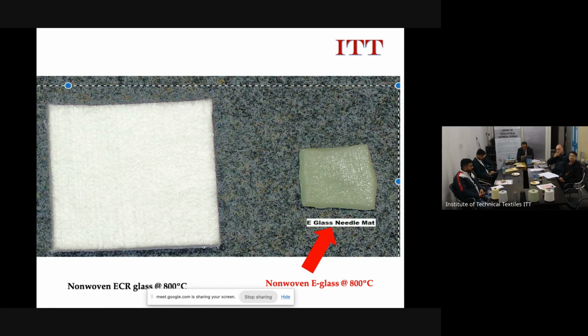But the moment you start doing tests at 700 degree and 800 degree centigrade, you understand that there are different types of glass available, and there are requirements where we have to do this testing at very high temperature. So this is just an example of testing performed overseas where e-glass starts shrinking at 800 degree centigrade, whereas another variety, ECR glass, is doing well. But like I said, we need to do our own R&D on different types of glass.